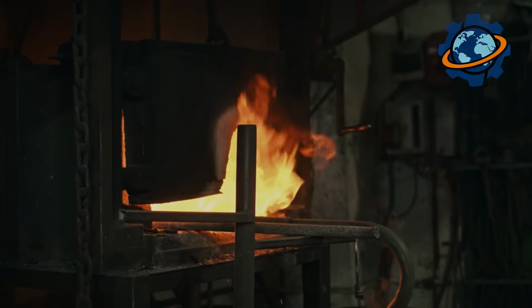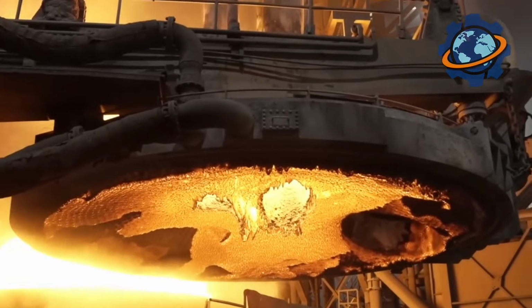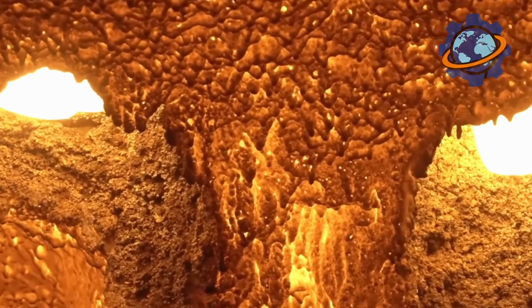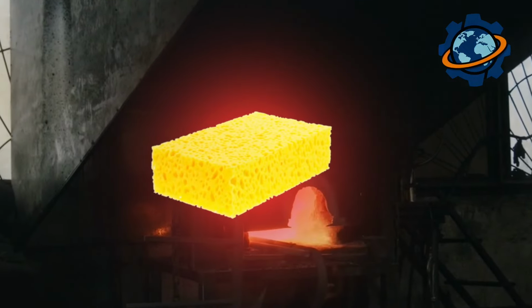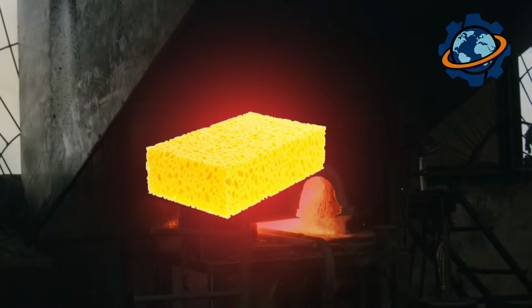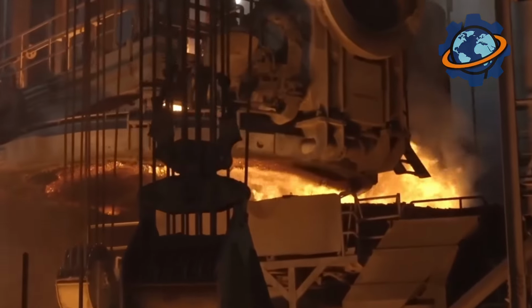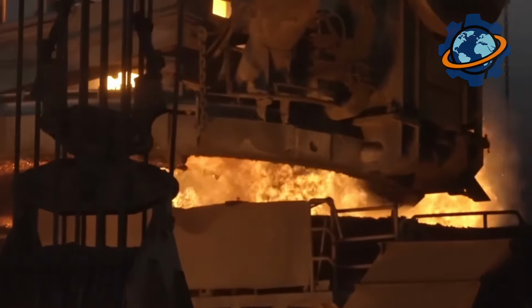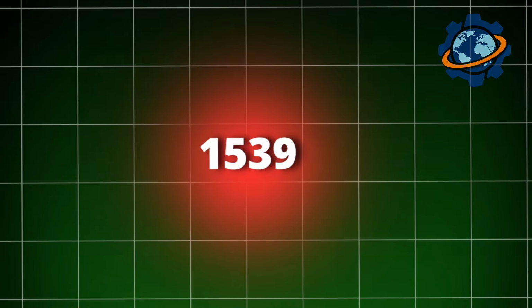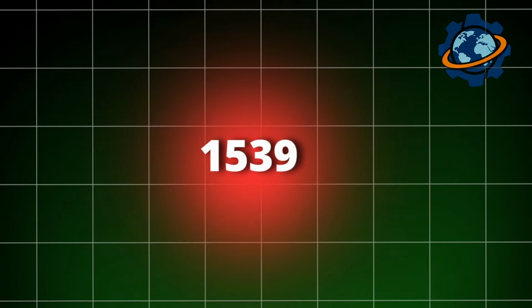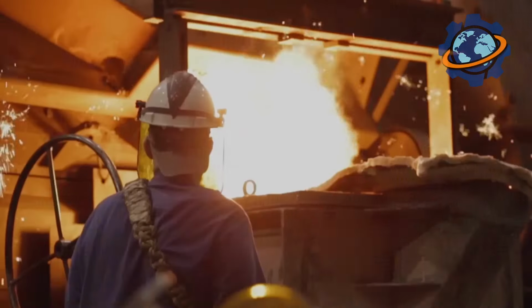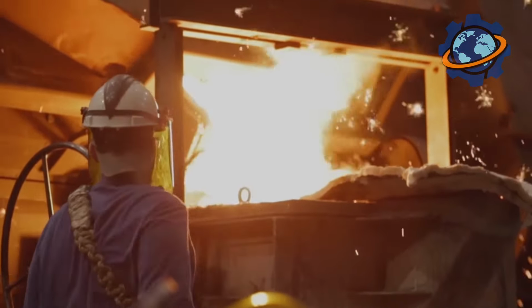The reduced iron continues its journey downward into hotter and hotter zones. It passes through the glowing layers of coke and, like a sponge, begins to soak up its carbon. And here's where something amazing happens. Pure iron melts at a very high temperature of 2,800 degrees Fahrenheit, 1,539 Celsius. But soaking up carbon dramatically lowers that melting point. That's why a blast furnace doesn't produce pure iron, but an alloy of iron and carbon, pig iron, which becomes liquid at just 2,200 degrees,